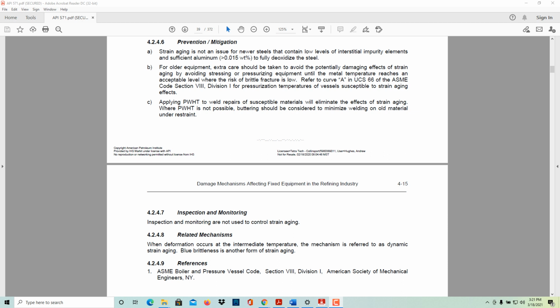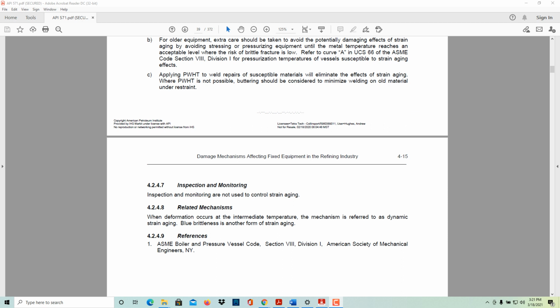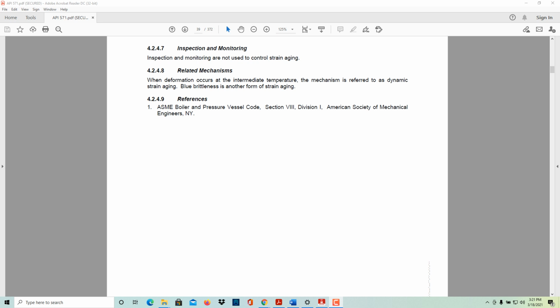Applying post-weld heat treatment to weld repairs of susceptible material will eliminate the effects of strain aging. Where post-weld heat treatment is not possible, buttering should be considered to minimize welding of an old material under restraint. Inspection and monitoring. Inspection and monitoring are not used to control strain aging. Related mechanisms. When deformation occurs at the intermediate temperature, the mechanism is referred to as dynamic strain aging. Blue brittleness is another form of strain aging.